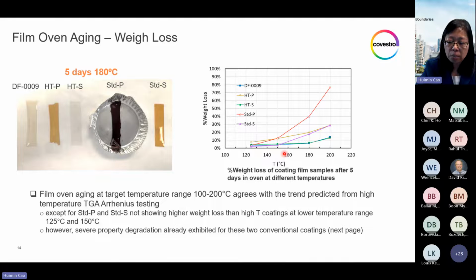And the conventional coating may undergo some hydrolysis process also going on. As a result of that, you will see in the next slide that the property measurement actually started to see severe degradation on the traditional coating, regardless of very low weight loss.